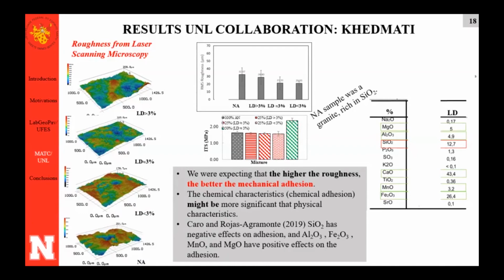So I took another slag that I had that is rich in silica to compare two different slags, one that's rich in this component and would have negative adhesion. We call it DP slag, has 32% of silica, so much higher than the LD, and other components more or less the same, and less iron, so it would be even more negative in terms of adhesion. This slag was the one that has the highest roughness, and if you just analyze roughness and you believe that the higher the roughness, the better the adhesion, you may be having results that you're not expecting in terms of mechanical performance.